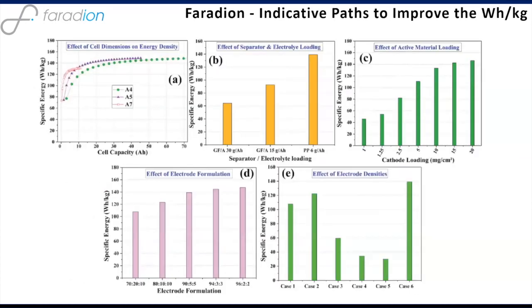And you might say to us, well, that's all well and good, just saying you're going to get to 200 watt hours per kilogram and beyond, but how do you think you might do that? Well, we have a lot of ways we're doing that right now. One of them is incredibly simple: the larger cells you can make, and because we have better safety characteristics, we can make larger format cells than is available for lithium ion. As you increase the cell capacity and the cell energy, you also get improvements in the packing efficiency of that cell. So that increases the specific energy in a very simple way.